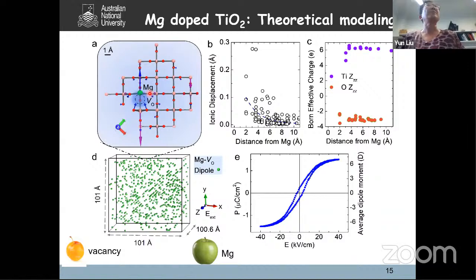As you can see here, this simulation result indicated that the ions surrounding titanium were moving off the center from the lattice sites. So as you can see, even titanium a few angstroms away from magnesium is still affected. Locally they change the structure, making this titanium dioxide lose the central symmetry. As a result, you can observe some ferroelectric behavior. Okay.